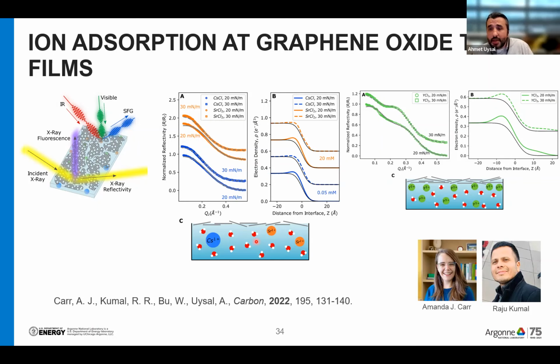And we would like to understand how ion adsorption would happen on graphene surface. And to be able to do that, we try to self-assemble graphene oxide at the air-water interface. That is the best way to create a thin film of graphene oxide and study ion adsorption on that. And we do these experiments again at sector 15 using X-ray reflectivity, X-ray fluorescence, and we also do some sum frequency generation spectroscopy experiments.